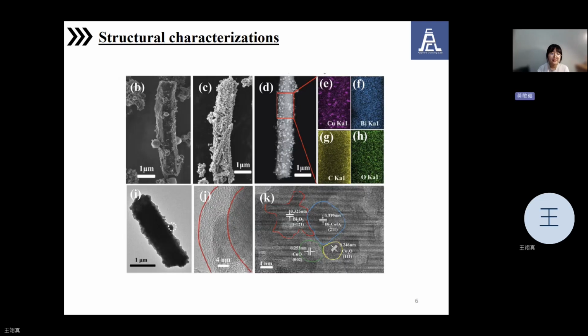And the picture shows the SEM and TEM images that confirm that the MOF-derived CuBi-75 retained a rod-like structure with uniformly distributed nanoparticles. CuBi-75 means 75% copper, and the element mapping on the right-hand side shows the homogeneous distribution of copper, bismuth, carbon, and oxygen.